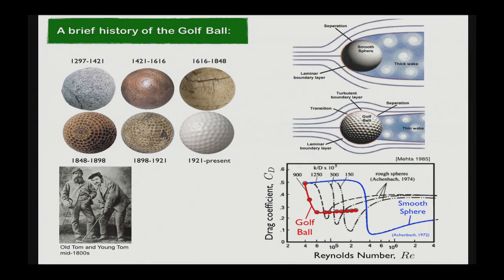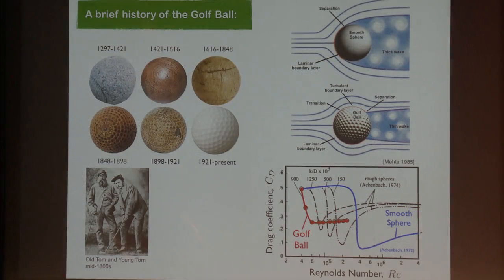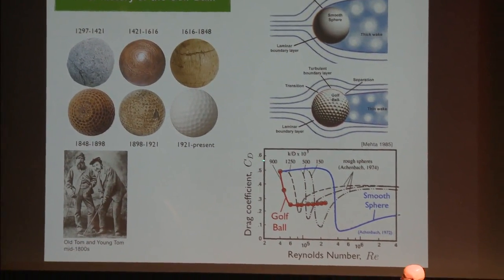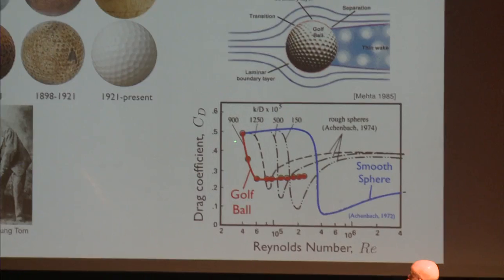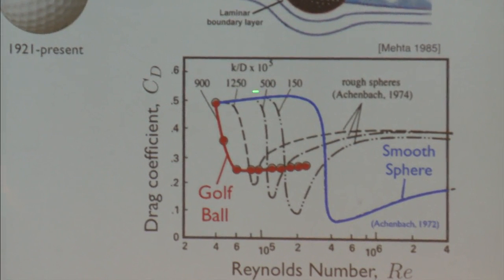So let me take you through these plots. So this is very classic data from Achenbach in the 70s. I'm plotting drag coefficient as a function of Reynolds number or flow speed. The blue curve is for a smooth sphere, so the drag remains fairly high in the range of around 0.5, over the range for which golf gets played. By contrast, a golf ball has a drag crisis much earlier, and over the range of golf actually has a lower drag by a factor of 2, so drag is 0.25. And if you play with the roughness of the sphere, you can have a different kind of behavior.